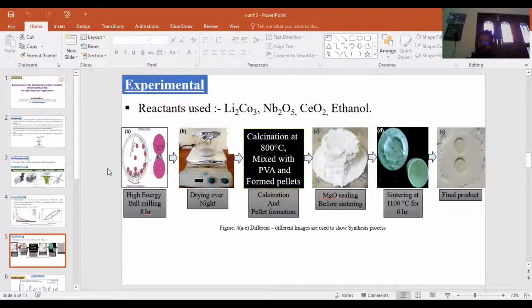Then I collected the sample and dried it overnight at 100 degrees Celsius. Then I calcined the sample at 800 degrees Celsius for 6 hours, and for pellet making I used a binder, which is PVA, and formed the pellets. Then I went for the sintering, and before the sintering I used magnesium oxide to provide a closed environment to sinter the pellets. I sintered the pellets at 1100 degrees Celsius for 6 hours. And in figure 4e, the final products are shown.